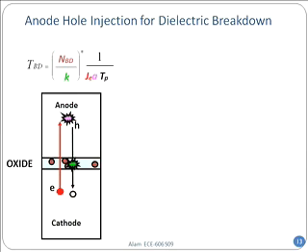So these days, what will happen is that electrons will tunnel from the substrate to the gate, and they will have impact ionization there, and the holes will come back in the reverse side, and in the process of coming back, they will break bonds. And this is called anode hole injection, because holes are coming back from the anode region.